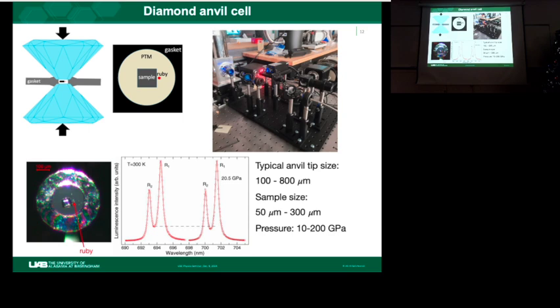So the ruby spectrum is calibrated to the pressure? Yes. It's typically done at a synchrotron. You know the equation of state of a certain calibrant, for example copper, platinum, silver, or gold. Or even very often we have neon pressure medium in here, and neon becomes solid at about 5 GPa. Based on the equation of state of neon, we can learn what the sample pressure is in there.